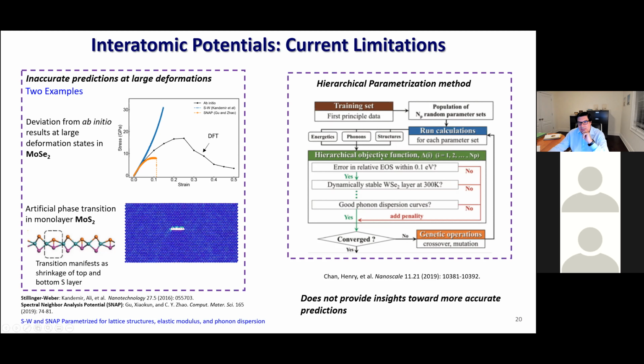So you start defining objectives of properties, like for instance, the equation of state, the stability at room temperature, the phonon dispersion curves. And first you make sure that you find through mutations and crossover that the error in the equation of state, for instance, is smaller than a certain value before you go and look at the next property. So it's very difficult to draw any conclusions about how these different potentials that you could adopt will behave in this cascade of properties. Will the potential ever reproduce properties within a certain error? And if you improve on one property, will it improve on all the others? Well, that's not clear in this methodology.